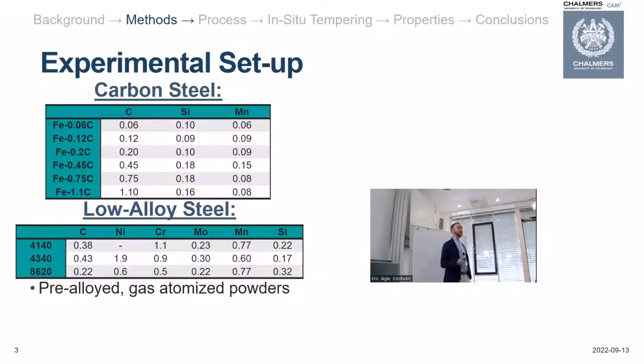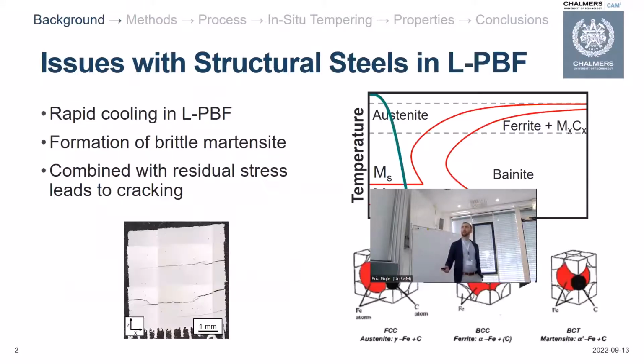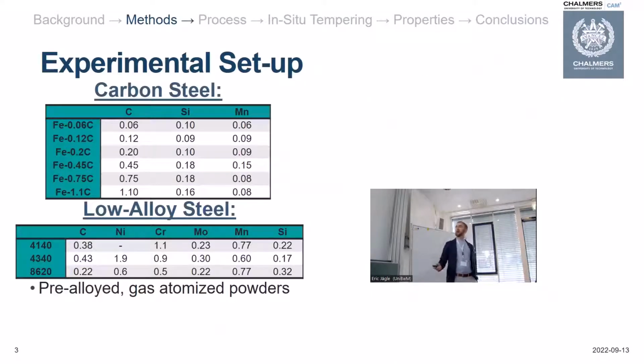But to carry out this analysis, we looked at a variety of materials. We first started with 6 plain carbon steels going from compositions of 0.06 to 1.1 weight%, so a pretty large range there. We also looked at 3 low alloy steel specimens. These were specifically the 4140, 4340, and 8620 grades. And there we went from about 0.2 weight% up to 0.43 weight% carbon. And these were pre-alloyed gas atomized powders that were supplied by Höganäs and Sandvik respectively.